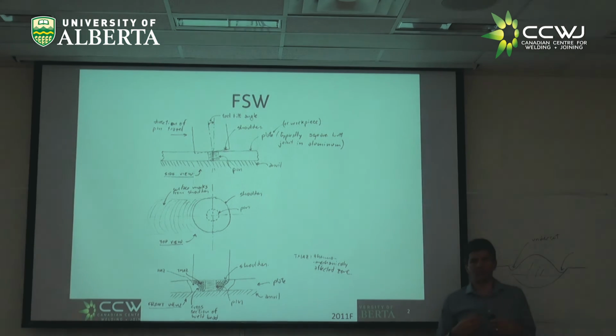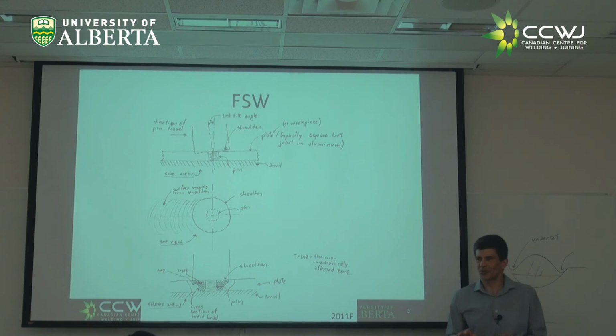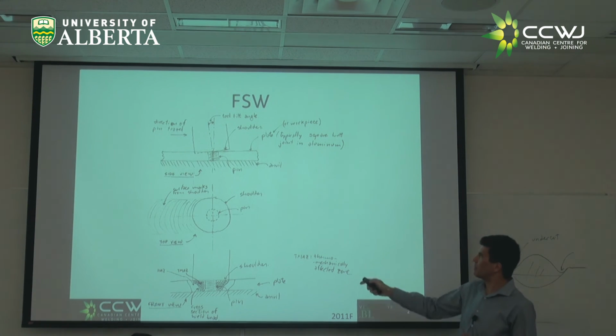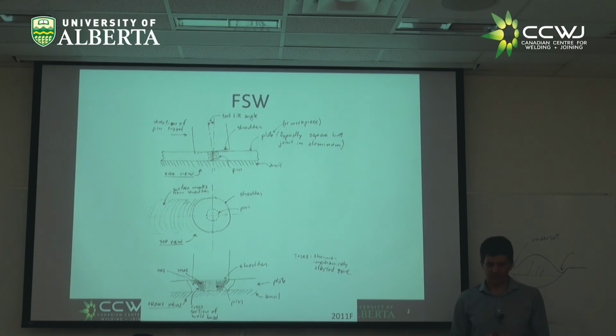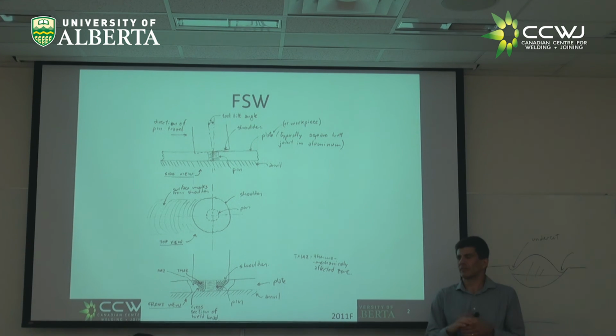And guess what? When I first heard about this, I thought people were wrong. But it's true, and we have it in the lab. If everything goes right, you'll see it. If I spin my pin, let's think of aluminum, something's going to get hot in there, right? Just the friction, for whatever reason, is going to get hot. Now, it's going to be hot locally near the pin, and outside it's going to be cold. So if it is hot locally, and this is intuitive, it's also soft locally, right? Because hot metal has lower yield strength, right? So if it is soft locally and I'm spinning, the deformation is going to catch on,